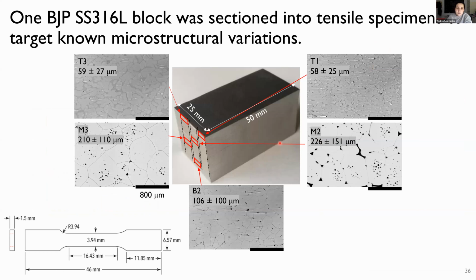So in order to analyze that further, we took some tensile specimens from an equivalent block. This is not the exact same block we had tested before, but it was a block created with the exact same conditions. We took them from different regions that we knew were going to have that varying response. We wanted some in the area where we had really small grains and almost no porosity, and some in the area where we had large grains and the pores were in the grains and the boundaries, but rounded and separated.